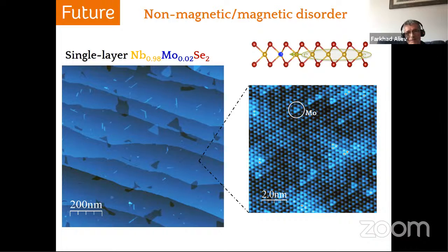So you're suggesting that these resonances may come from the fact that the system is confined? Yeah, these resonances, for example, when the electron hole pairs are confined in superconductor, they have named Tomasch resonances. And I don't remember exactly, when they are confined in the electrode close to superconductor, they have another name, but they were well known. We observe experimentally the same resonances in 40 nanometer thick vanadium superconductors when there is an electrode like iron, which is confined with two barriers. So, and our resonances have also many periods, etc., etc.